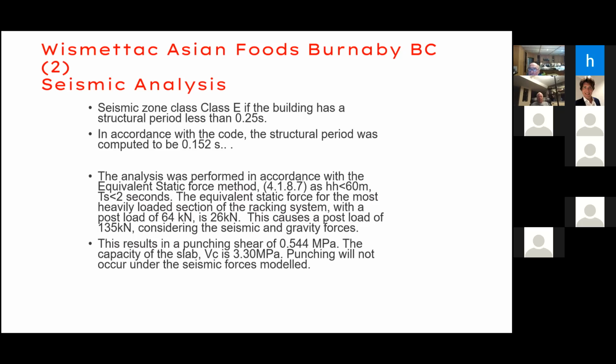Yes, I wanted to add to this, Kevin, that the Burnaby freezer is showing a monolithic slab which extends 26,000 square feet. And because of the owner's requirement, the footprint for that slab looks like a piece of a puzzle with many re-entering corners, which we all know are consistent with crack initiation. In this case, all these corners are treated with certain details, but the message is you now have an owner that can operate 26,000 square feet, a little bit more than 2,400 square meters, without one single seam or joint, and as a matter of fact, in Burnaby, without cracks. Now, concrete cracks, but we never sell crack-free or promise crack-free; we look at lowering the probability of cracking drastically.